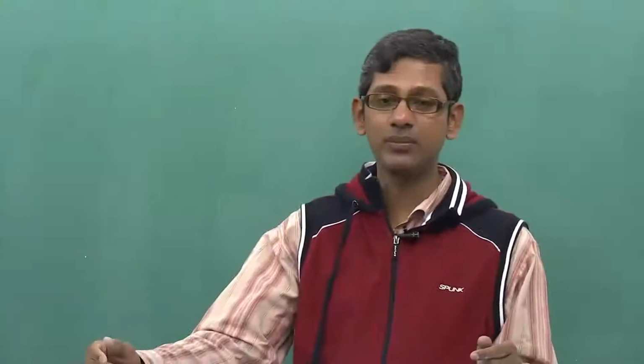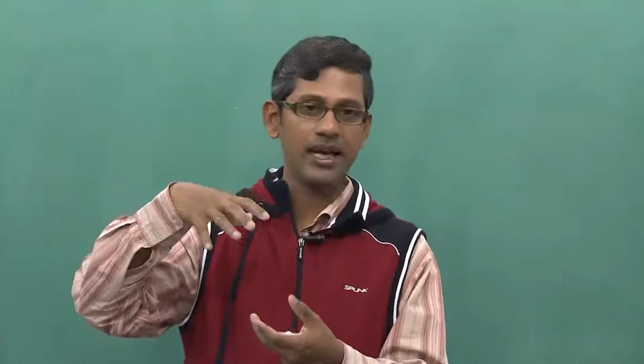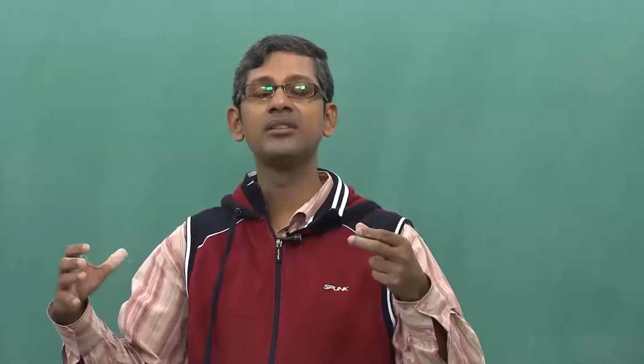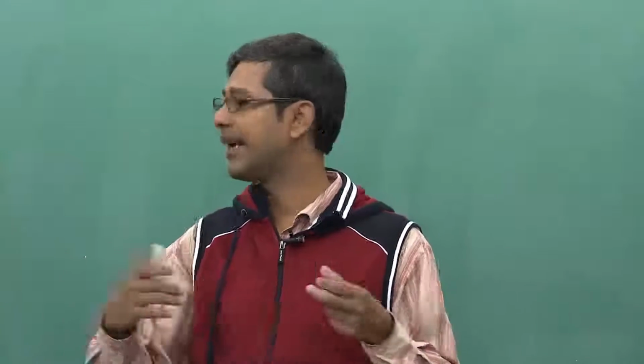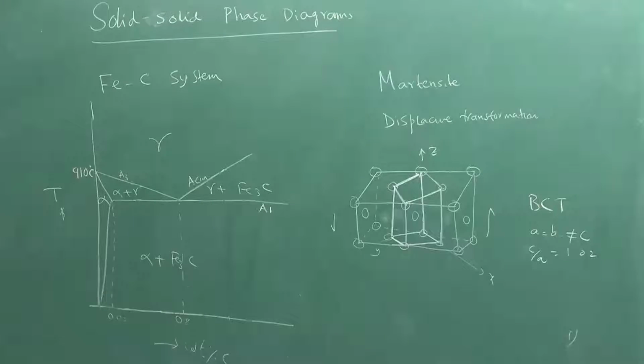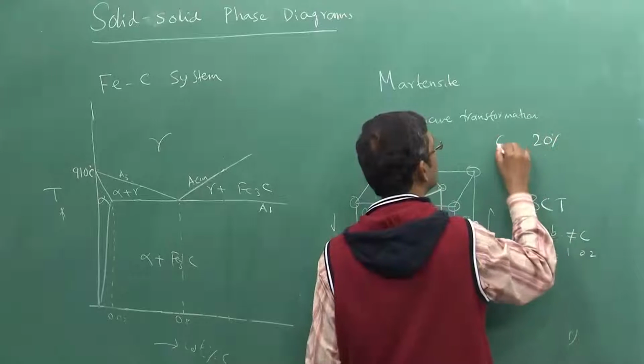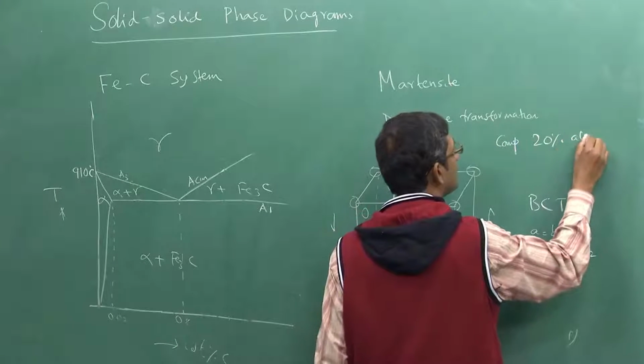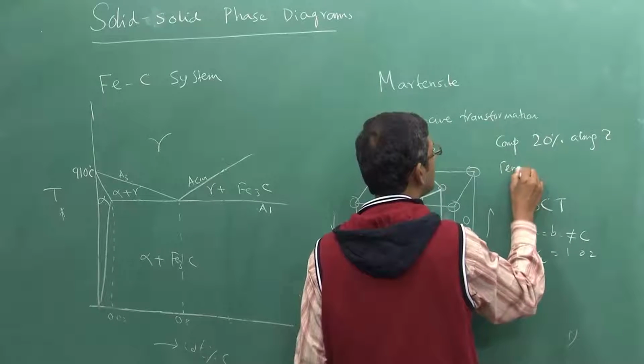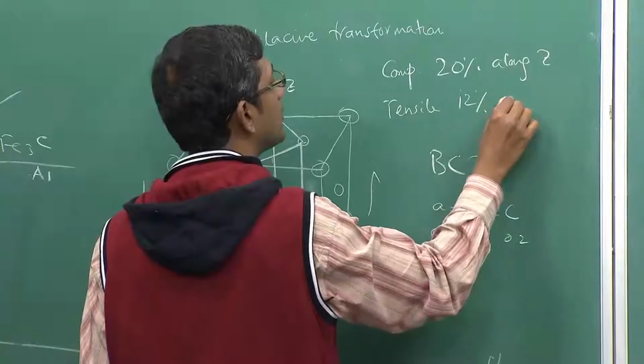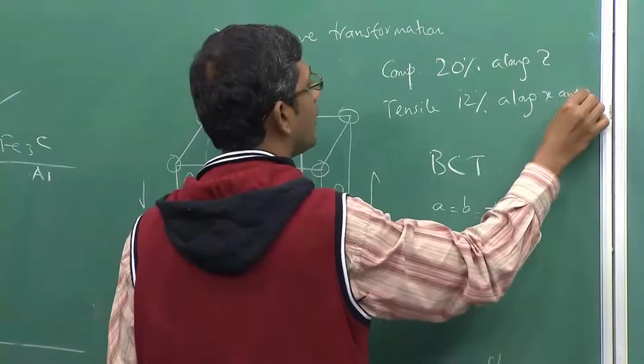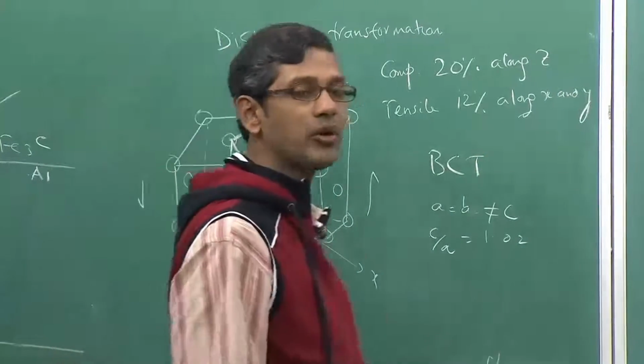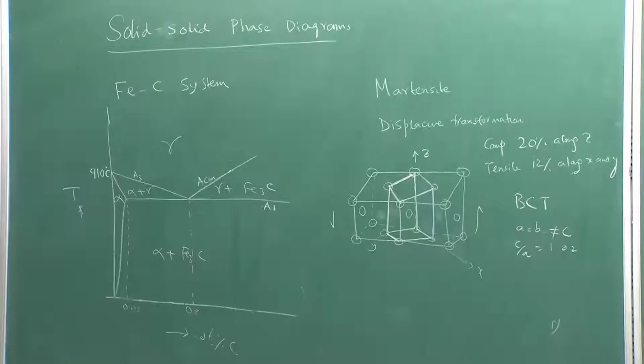In the case of plain carbon steels, there is a 20% compression along the C axis and tensile strain along the x and y axes. So along the z axis there is 20% compression, it will be compressed. On the other hand, along the x and y axes there is 12% tension, let me write it down. So 20% compressive strain along z, but tensile strain of 12% along x and y. This is the amount of strain applied, and this strain leads to change of crystal structure. Just by flipping atoms you can change this crystal structure, correct.